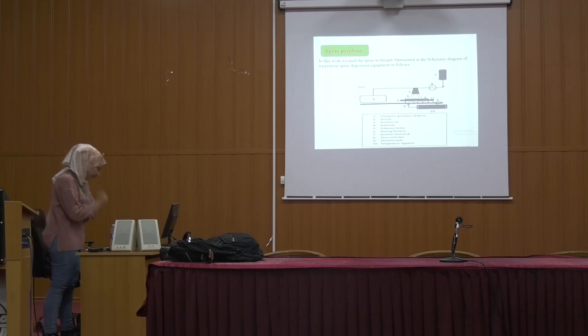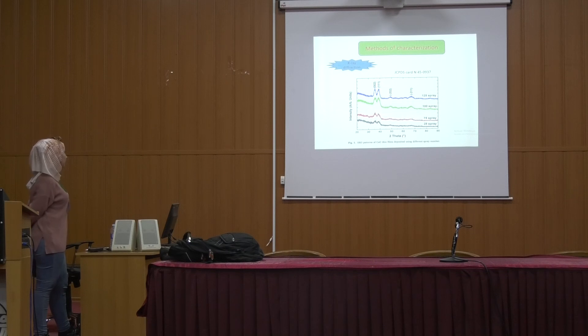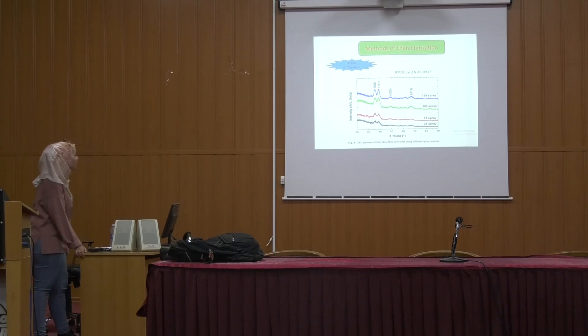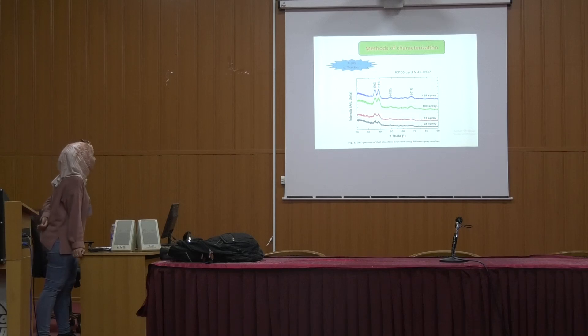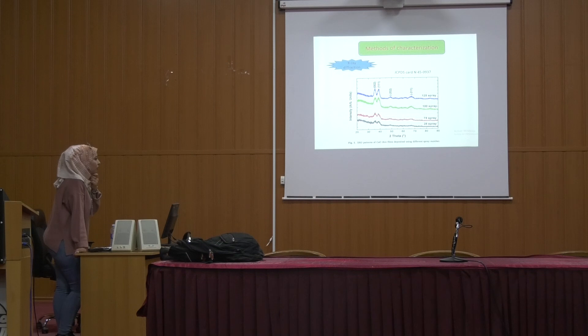Methods of characterization. Firstly, X-ray diffraction. The XRD pattern shows the presence of four peaks: (002), (111), (-202), and (-311), confirming that the films have a monoclinic structure corresponding to CuO, according to JCPDS card number 45-0937. No peaks corresponding to the Cu2O phase have been observed.